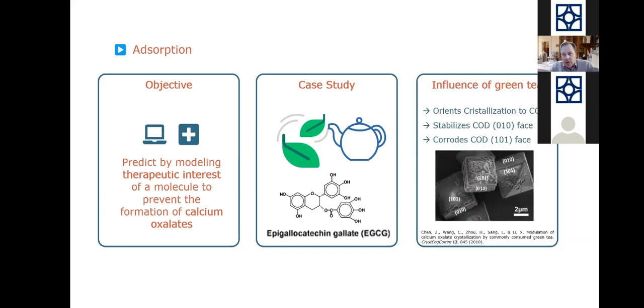Okay, and here is a picture. So we can see that. I see you see my cursor. You see these pyramids that you've seen for the COD structure, the calcium oxalate dihydrate structure. You see that there are some craters. It's like a start of dissolution, of corrosion. This means that there is an additive that makes a complex with the surface and is so strongly adsorbed that it takes out an ion, a calcium ion in particular, and we will try to have a molecular view on that in the next slides.